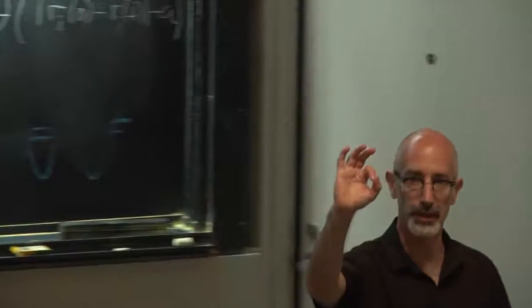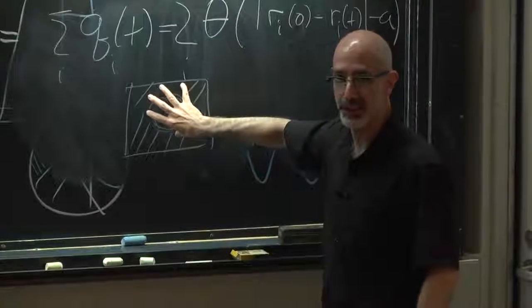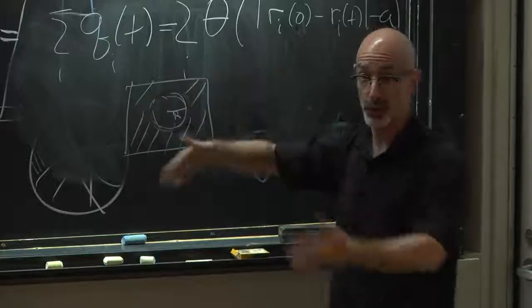So if the ball is literally one particle wide, there's one configuration, the overlap is unity. And then if I make this sphere bigger and bigger, then the boundary effect from the frozen particles on the outside of the ball will have less and less influence in setting what the actual configurations inside the ball can be, and the overlap will go to 0.